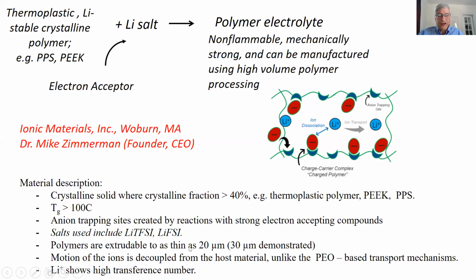We can make these films as thin as 20 microns. Right now, we're down to 30. And we have a new transport mechanism. The motion of the ions is now decoupled from the host material, unlike in the polyethylene oxide, where the polymer chains and segments have to be moving for the ions to move.